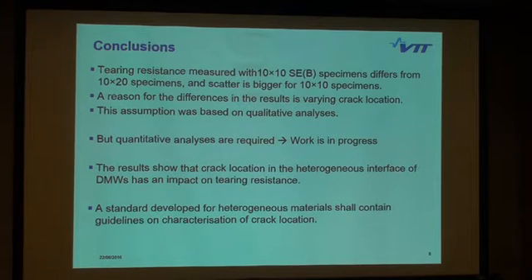So, to conclude, what we saw in the graphs, in the results, was that the tearing resistance of the 10 times 20 specimens and the 10 times 10 specimens differ, and the scatter is also different. And a reason was clearly seen in one case, that the reason is the crack location. But now a problem is that these analyses were based on a qualitative assessment. A quantitative assessment of the real crack location is needed to really see the distance from the crack location to the fusion line.